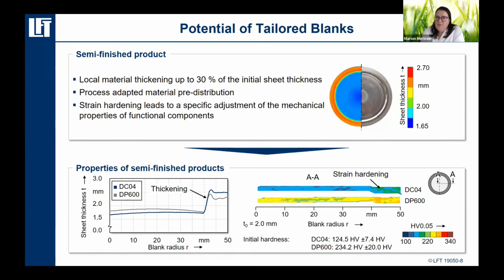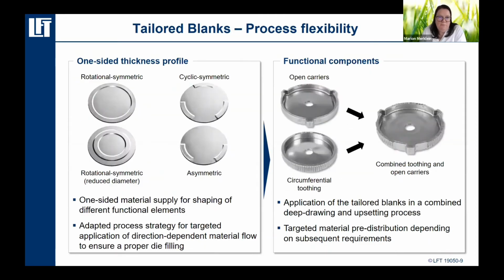And 30% I think is a real good and interesting number. And with the increase of the sheet thickness, of course, we have a strain hardening effect in the material, which means that we change the mechanical properties, for example, the yield strengths and the tensile strengths. So these typical material values are also increased by between 20 and 30%. That depends on the work hardening exponent that is characteristic for the material. As an indicator for this, you can see here some hardness measurements, because you can directly correlate the hardness and the yield strength of the material.